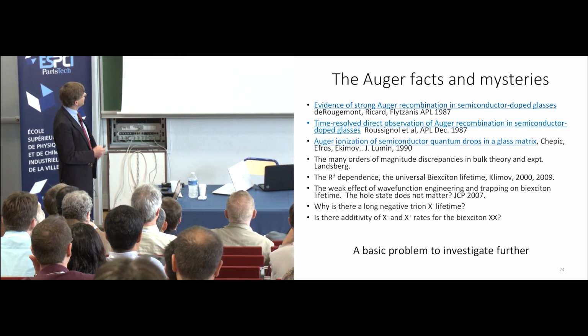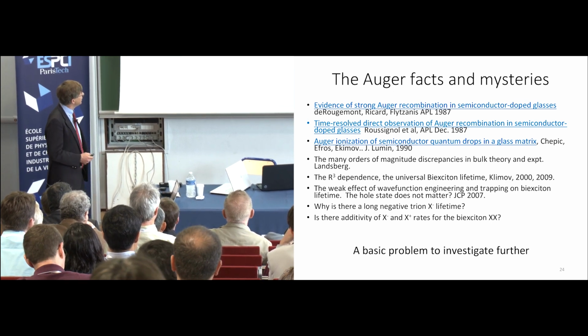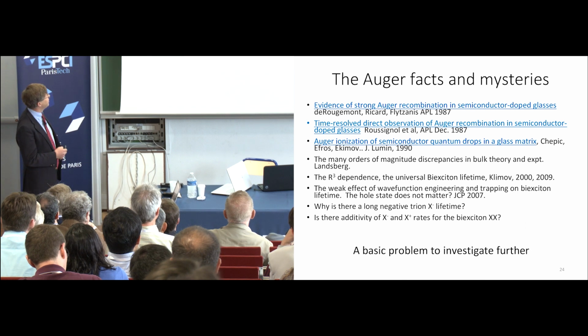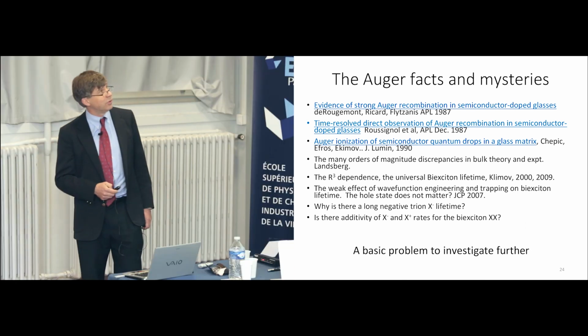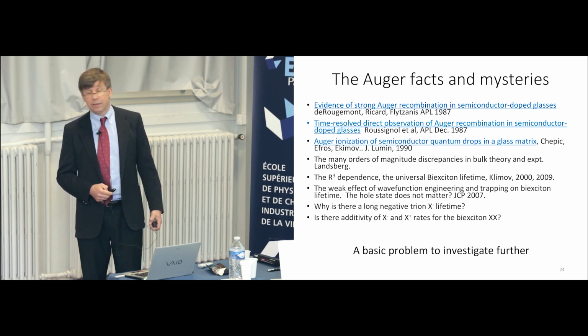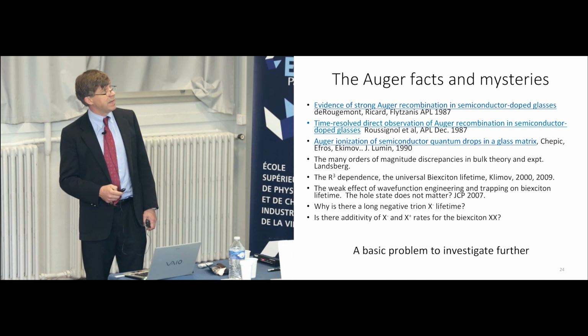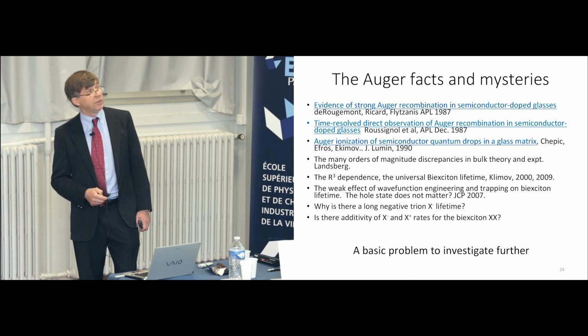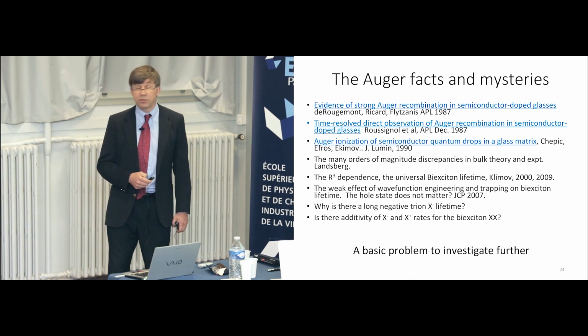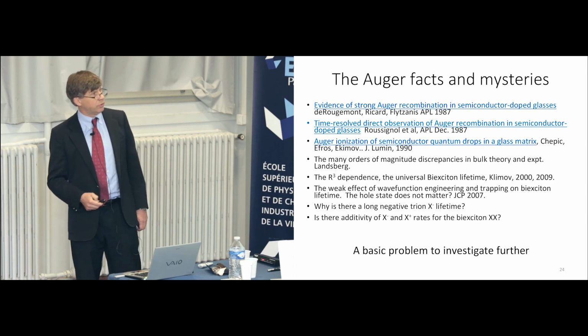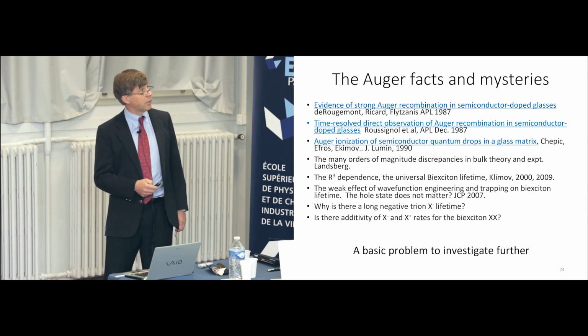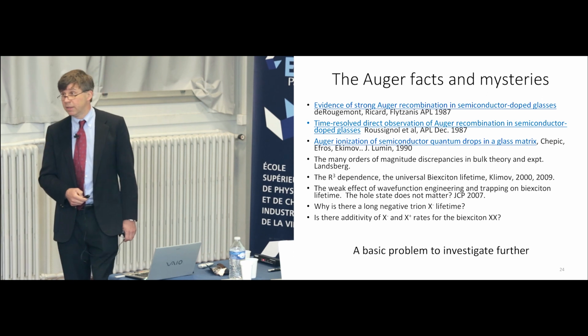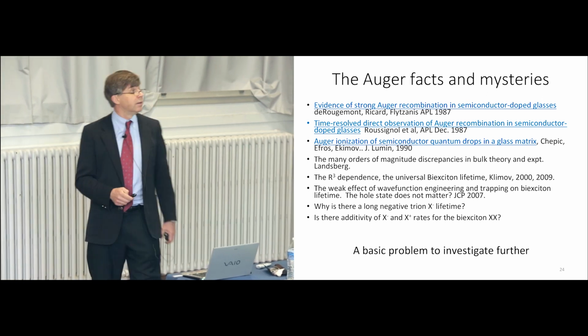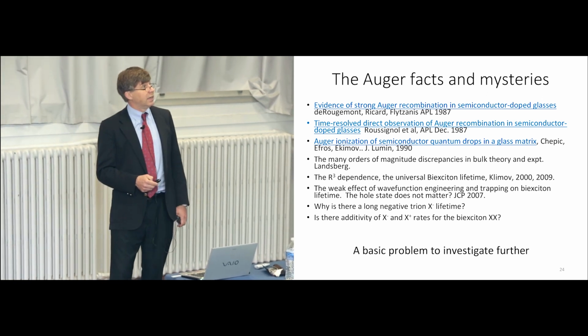So I'd just like to mention some of the Auger facts and mystery. It was very nice to see Sasha mention this early work from the Palaiseau group. And then I'd like just to say that there are many things that are not clear in Auger, at least to me. There are many orders of magnitude discrepancy in the bulk theory and experiment calculation of Auger rate. There's, of course, the beautiful results of Victor Klimov, the R-cube dependence and the universal biexciton lifetime, which makes absolutely no sense to me, but it seems to be a fact.